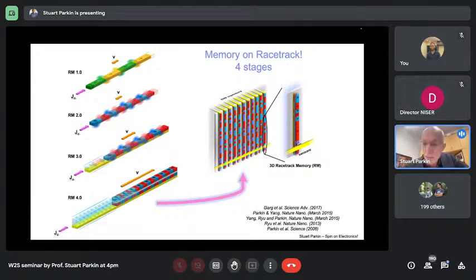And so I had originally proposed for a spin valve, it was the same problem, that the two layers in a spin valve are strongly coupled by dipole fields. And in fact, they'll either be parallel if the moments are on top of each other, or if you have two moments on the side, they'll be antiparallel. Anyway, so it means that if they're in plane magnetized, they'll be antiparallel. If they're perpendicularly magnetized, they'll be parallel oriented in two layers. You have to eliminate these dipole fields, which increase inversely with the size of the device. So we did that by this invention of mine of a synthetic antiferromagnet.